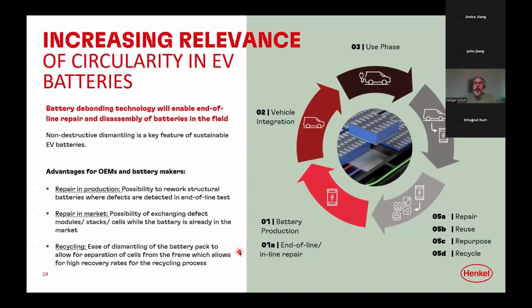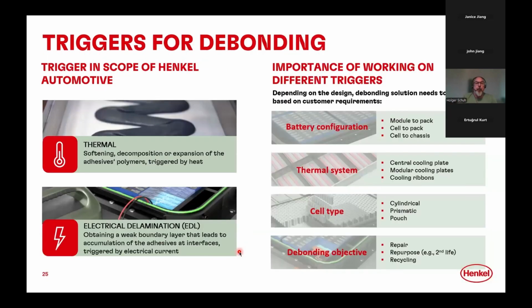And when you look now at the trend that we are bonding everything together for lifetime reliability, there needs to be a certain mechanism that you also, dedicatedly in certain areas, in case of a failure, could do the debonding, to make the battery repairable. And we're addressing this with two different triggers. One is a thermal trigger, which is actually a coating at the dedicated areas, which will then be triggered thermally and creates an adhesive failure either on the structural or on the thermal adhesive between the two components.